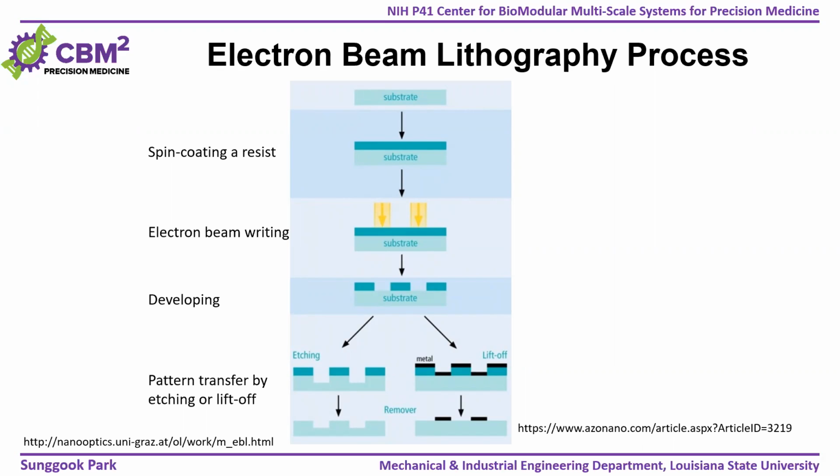on the resist. Then as we discussed in photolithography, depending on the type of resist, whether this is positive resist or negative resist, the exposed area will be either broken or cross-linked, more hardened, right? Then we do the same developing process, and now we will have patterns. But since we use an electron beam, we can make patterns very, very small. Practically you can make patterns down to 10 nanometers, but some papers show that they produce patterns down to like 4 nanometers.